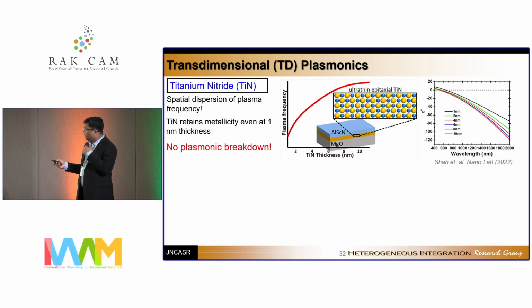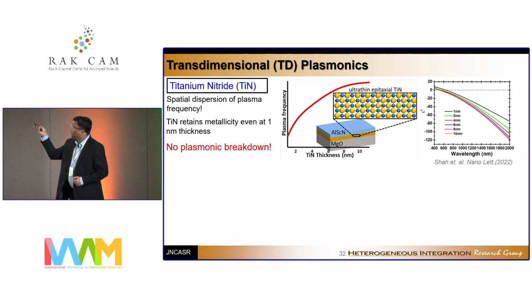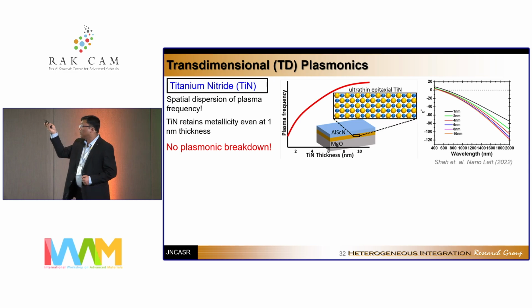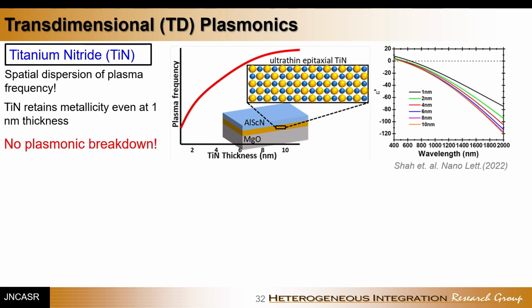So what we did is that we first tried it with our titanium nitride. Titanium nitride, again, looks like gold, acts like gold, and in fact we have developed it as a replacement for gold for visible range optical applications. So when we reduce the thickness of titanium nitride from 10 nanometer to 1 nanometer, you see the material still retains its plasmonic characteristic because the epsilon ENZ crossover, the epsilon near zero crossover as we call it, still exists in all the materials, but the plasma frequency is shifted, and that's basically the spatial dispersion of plasma frequency, which the theory predicts. But there is no plasmon breakdown. The localization is still not strong enough to cause any plasmonic breakdown.